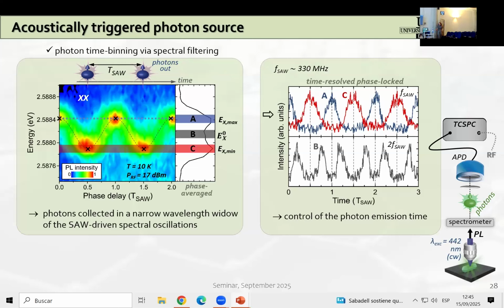So if, for example, we would collect the photons at this maximum or minimum energy of this acoustically driven spectral modulation, we would see that these two emissions are out of phase with each other and that the photons are emitted at the acoustic frequency. If, on the contrary, we collect the photons at this equilibrium central energy here, the emission will take place twice per acoustic cycle, at twice the acoustic frequency. This is because the emitting states, as you can see by these marks here, move past this energy twice per acoustic cycle. So in this way, we can control acoustically the photon emission time.